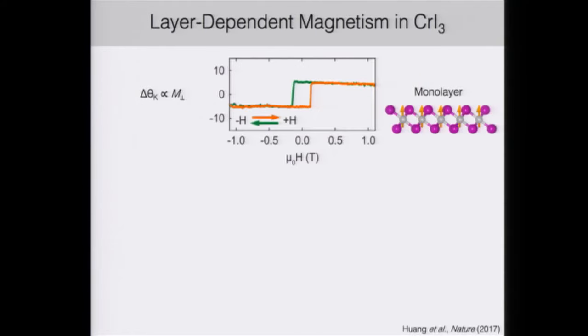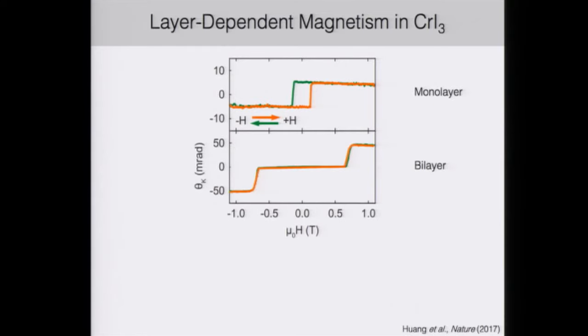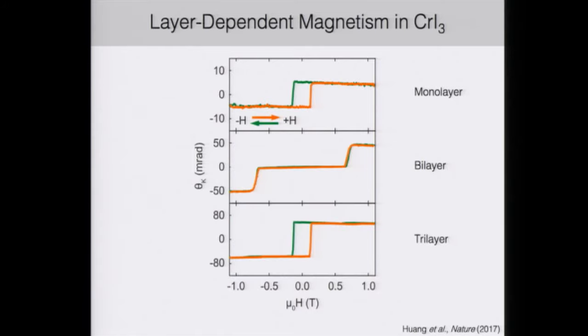So when we do so with monolayer chromium triiodide, we see this very beautiful ferromagnetic hysteresis loop. So this is consistent with an Ising ferromagnet behavior where the spins are pointing perpendicular to the layer. And this is exactly what we would expect if we were to take a bulk ferromagnet and cleave it down to the atomically thin limit. However, we see something different when we look at bilayer chromium triiodide. So here, the Kerr rotation actually vanishes at zero applied field and only gets a non-zero signal once we apply a much larger magnetic field. And then when we look at a trilayer flake, we return to a net moment at zero applied field. And so this result,